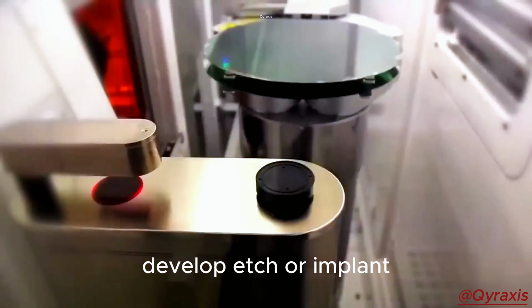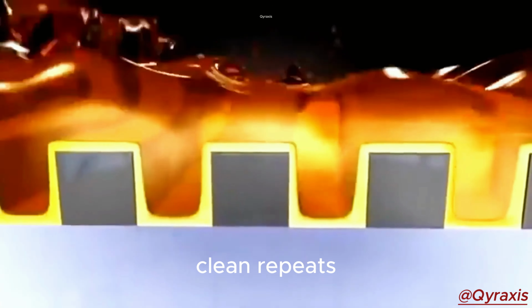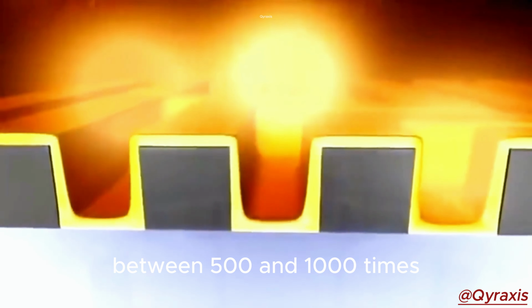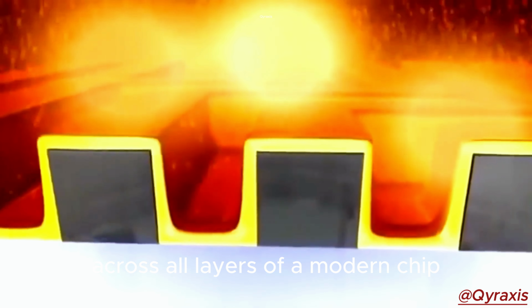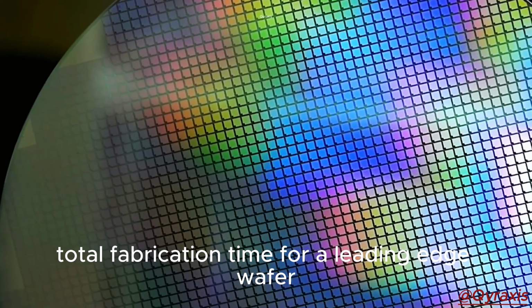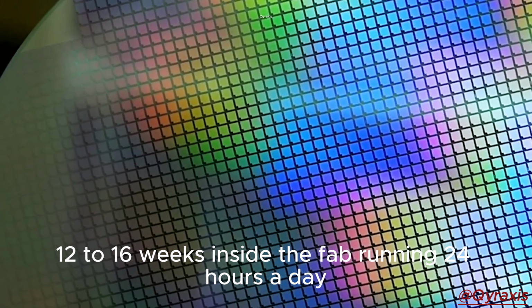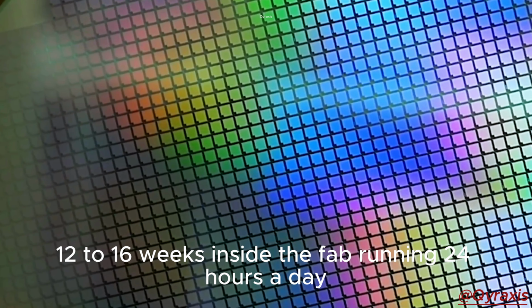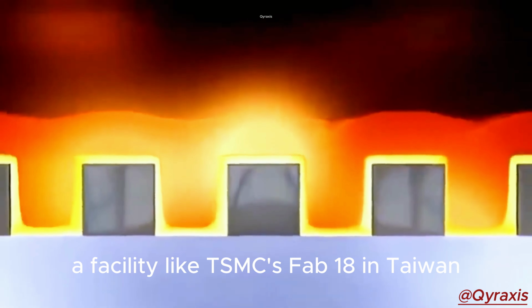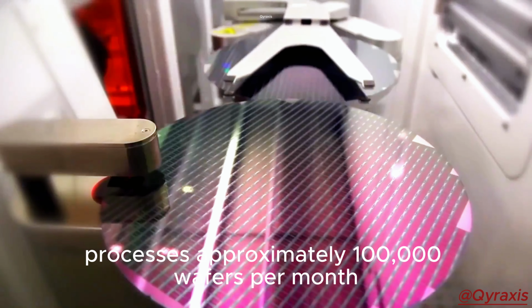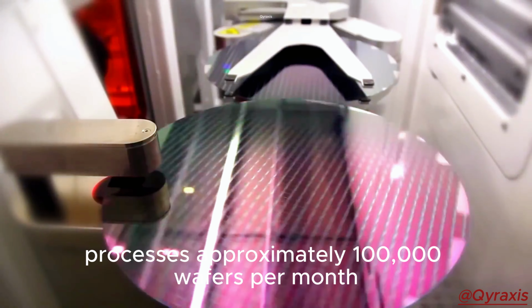This full cycle, deposit, expose, develop, etch or implant, clean, repeats between 500 and 1,000 times across all layers of a modern chip. Total fabrication time for a leading-edge wafer, 12 to 16 weeks inside the fab, running 24 hours a day, 7 days a week. A facility like TSMC's Fab 18 in Tainan processes approximately 100,000 wafers per month.